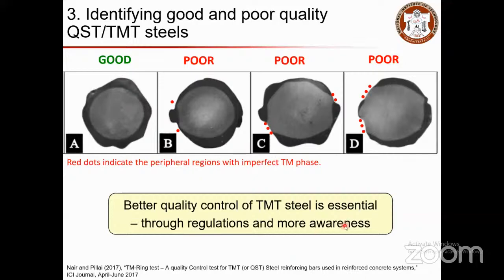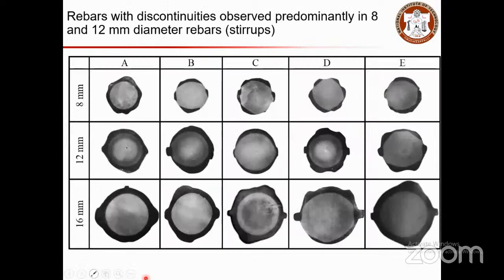Professor Pillai works extensively on TMT quality assurance testing. A test method has also been proposed based on the same TM ring test, as a quality control test for TMT bars. We collected a lot of rebars from different manufacturers to check how good the bars in our market are. What we observed is that certain manufacturers are doing well, and their products satisfy the required criteria by providing a uniform TM ring with the proper soft FP core. Whereas for other manufacturers, the quality is not met.